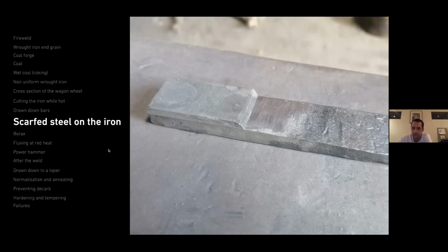And then in this image, you can see there's the hard bit of steel laid on top of the iron, and there's a mild scarf cut into the edge of the hard steel. And as you heat it up and hammer it down, this prevents a cold shut from forming at that intersection of the steel and the iron. If the steel is left square there, it just sinks down into the iron and it leaves a cold sort of crack, which is really not desirable. So this scarf is an important step in getting it all even and smooth.